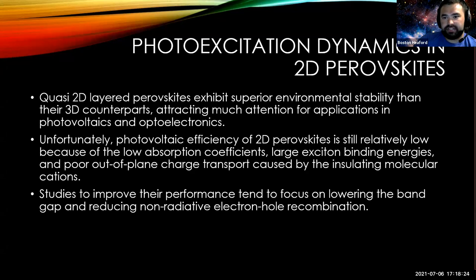And the reason for study into it is because 2D perovskites show much higher environmental stability than their 3D counterparts, which makes them much more desirable in many applications. Unfortunately, the photovoltaic efficiency of the 2D perovskites is still relatively low because of low absorption coefficients, large exciton binding energies, and poor out-of-plane charge transport. So studies to improve their performance tend to focus on lowering the band gap and reducing the non-radiative electron hole recombination rates.